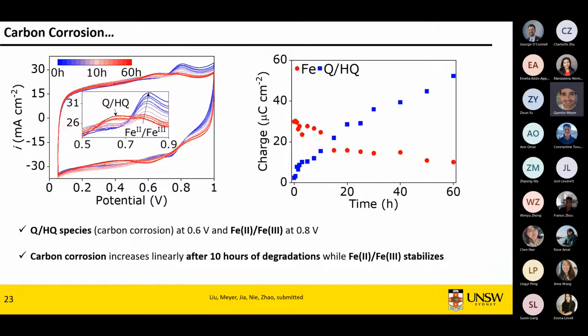So to capture carbon corrosion, we did some cyclic voltammetry. We saturated the cathode side with nitrogen, and we kept the anode with hydrogen as a reference electrode. And this is what we obtained. We obtained these kinds of peaks. This peak corresponds to the iron redox peak. This one corresponds to quinone and hydroquinone products, which are basically carbon-based species that form during carbon corrosion. They've been well identified in the literature and linked with carbon products. You can see that the iron peak is very big at the beginning, then it gets very small very quickly. This peak increases eventually. Initially, not a lot of increase, then it increases a lot.